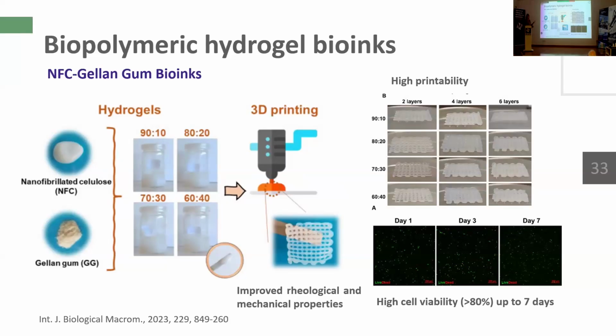In this area, our goal was to test new formulations, to exploit polysaccharides that alone are not able to be printed. For example, as in this study, we use gellan gum. The gellan gum hydrogels are very fragile. So when we incorporate nanocellulose, we are able to increase the printability, to obtain 3D constructs, and to have a high cell viability after 7 days post-bioprinting, here using skin cells. So this work focused on this new formulation and on using another polysaccharide to enlarge the diversity of available bioinks.